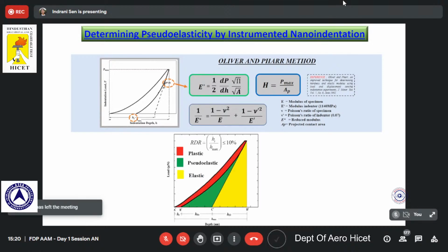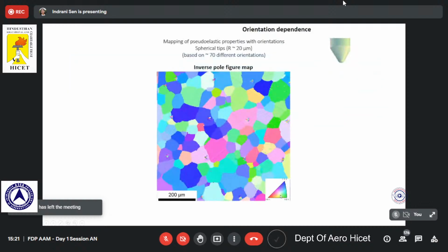Now, in the case of a shape memory alloy, very interestingly, it will show a P-h curve something like this. You can see the red one, which is fully plastic, this one here, A prime, B prime. And for this one here, the entire part, the green and the yellow, has been recovered. This is the recovery displacement, or depth of penetration, for the case of nano indentation of nickel titanium. Out of that, the yellow part is the elastic one because it follows the elastic modulus, and the green one is the pseudo-elastic one. Based on this understanding, we did indentation on different grains having different orientations.